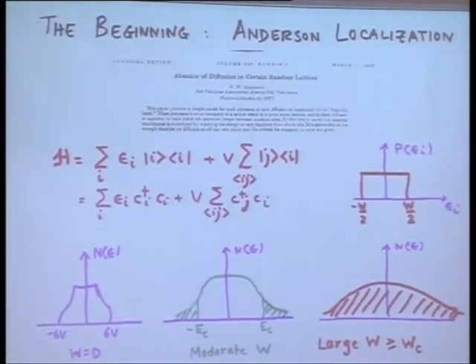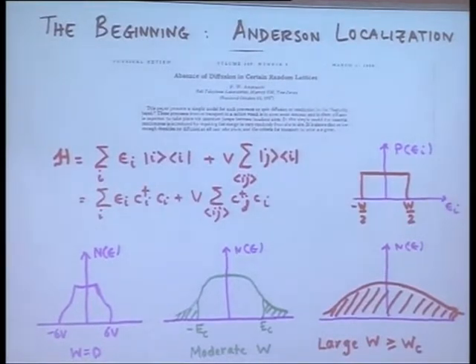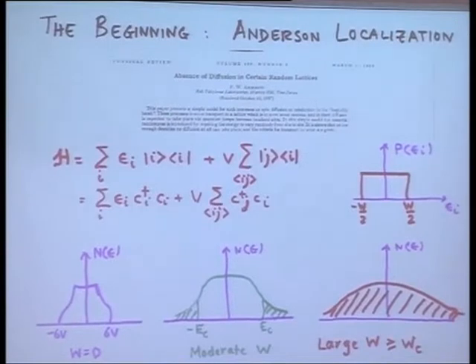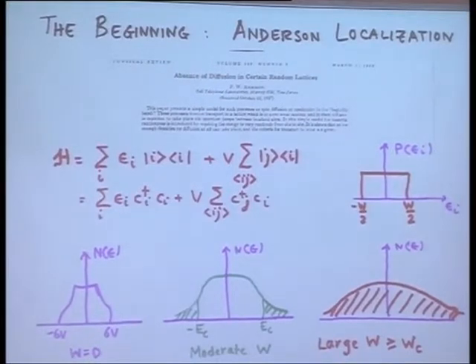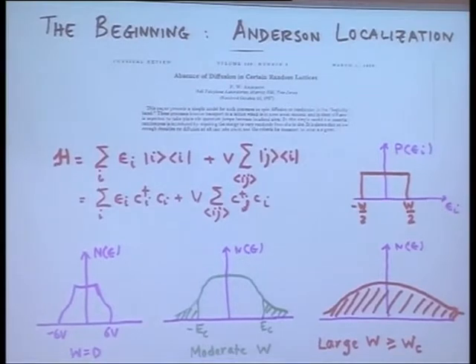Now, to the other half, which is Anderson localization. The other viewpoint of the metal-insulator transition, from Anderson's abstract paper in 1958 for which he got the Nobel Prize, is just a one-electron problem. What you have is a Hamiltonian with on-site energies distributed independently and randomly — the box distribution or uniform distribution between minus W/2 and plus W/2 — and hopping on a bipartite D-dimensional lattice, such as simple cubic or square lattice.